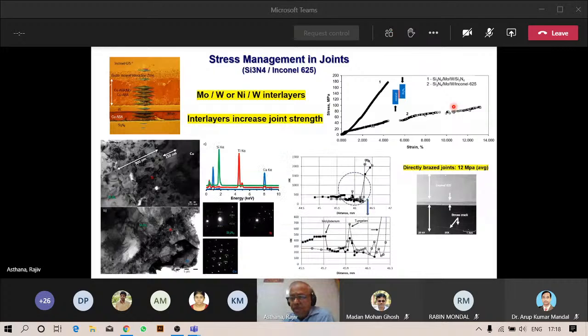So in this stress strain plot, to figure out the bond strength, curve number 2 shows the behavior of silicon nitride to Inconel bonded using moly and tungsten. So compared to very low strength here for directly bonded joints, we get higher bond strength, about 80 or 90 MPa, which is not very high, but still much higher than what we get in a directly bonded joint. Now, to actually optimize the bond strength, we will need to play with the thickness of these interlayers and other parameters. We haven't done that. We, in fact, focused more on the interface in the system. So this is one way to manage stress by putting interlayers.